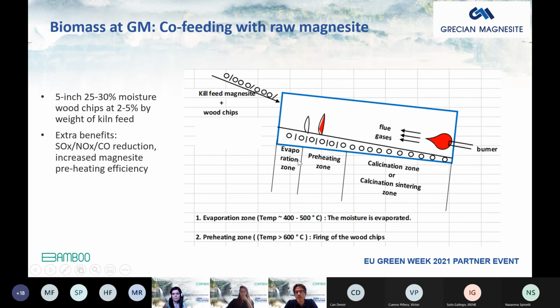There is the evaporation zone here, which at around 400 to 500 degrees Celsius, all of the moisture of the kiln feed is evaporated. And then there is a preheating zone at temperatures more than 600 degrees Celsius, where there is combustion of the wood chips. And this whole evaporation and preheating zone contribution helps us in reducing the thermal load required for the fuel injected through the burner.